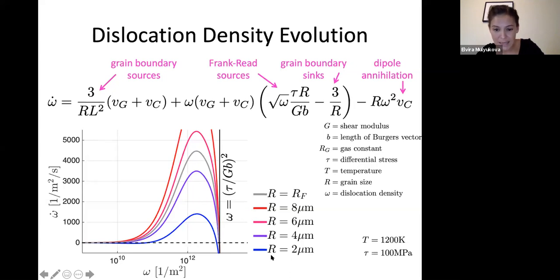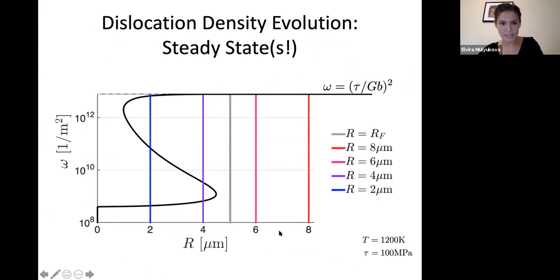However, once the grain size is relatively small, where these terms that I've delineated before that depend on grain size become more dominant or more significant, there is, in addition to this steady state that is close to the one for larger grains, also a new steady state that the system may tend towards. So this is another steady state dislocation density that you may see in a finer grained material. This result is easier to show in this plot here, where I'm just plotting the steady state dislocation density versus grain size. This is the same plot as I showed you previously, but now versus grain size.